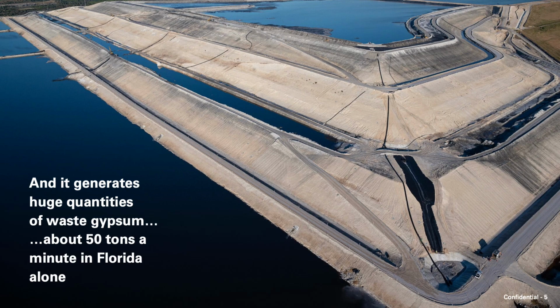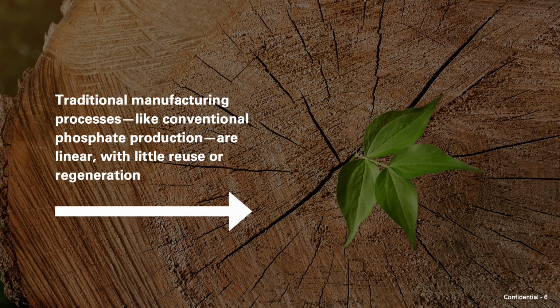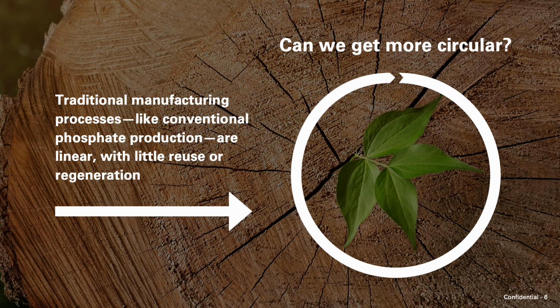And let's not forget that the wet acid process generates a lot of phosphogypsum waste, about 5 tons for each ton of phosphoric acid. Where does this waste phosphogypsum go? Well, much of it goes into waste disposal stacks. There are 25 of these in Florida alone, growing at about 50 tons a minute. Like many other industries, phosphate manufacturing is a linear process where wastes are neither recycled nor reused. Can we get more circular in the phosphate sector?